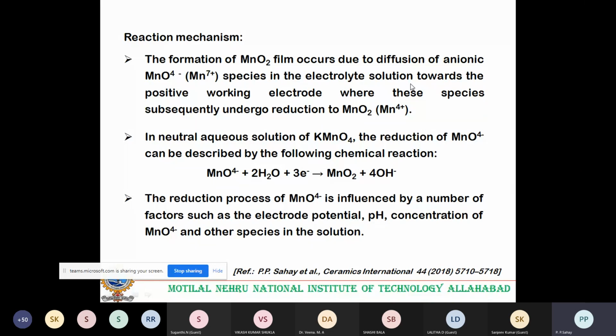So since it is an anion, MnO4 minus species in the electrolyte solution move towards the positive working electrode, where these species subsequently undergo reduction. Look at this reaction. This is the reaction which occurs at the substrate surface: MnO4 minus plus 2H2O, and so MnO2 film is formed. The reduction process is influenced by a number of factors, such as the electrode potential. Electrode potential means the 0.2 volt I put in the potentiostatic case. It also varies with pH and the concentration of MnO4 minus. I recall that I used 0.1 molar concentration of the KMnO4 and other species in the solution. So this is the reaction mechanism.